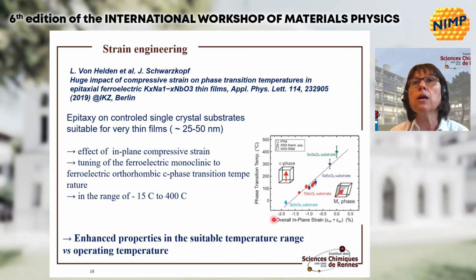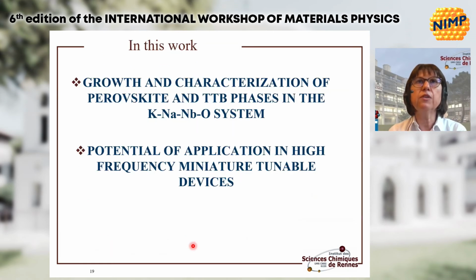And by strain engineering, as we can see here, it's possible to strongly change the phase transition temperature. This phase transition temperature corresponds to the pseudomorphic transition. That means that both phases, before and after the transition, are ferroelectric. This is the effect of the in-plane compressive strain, and the impact is huge. As you can see here, it's possible to tune the temperature of transition between minus 15 degrees C and 400 degrees C. So it's possible to enhance the properties, because it's possible to bring the transition temperature close to the operating temperature and enhance the physical effect this way.